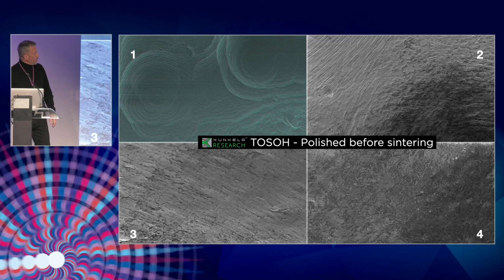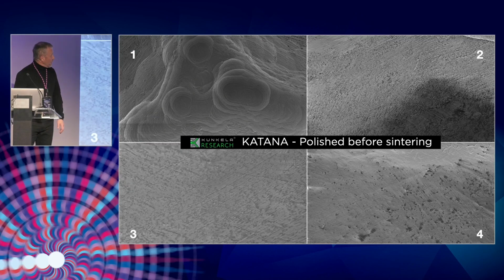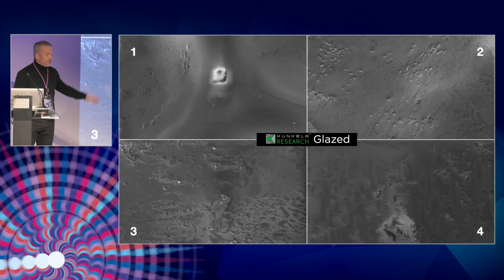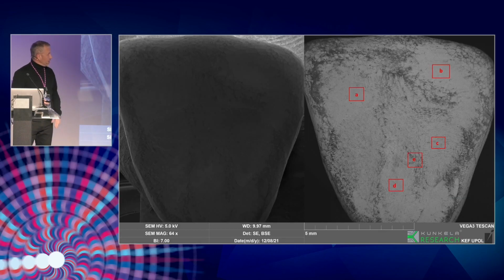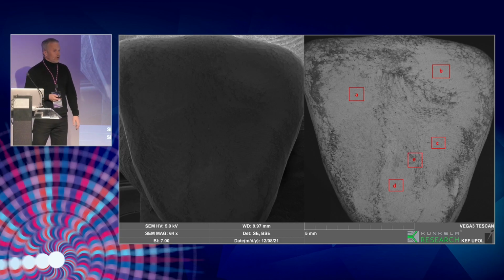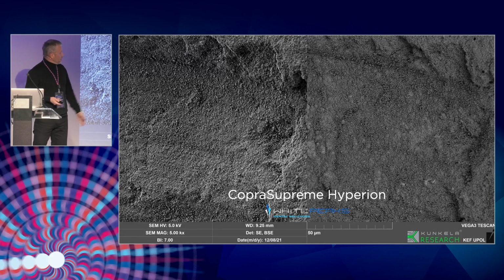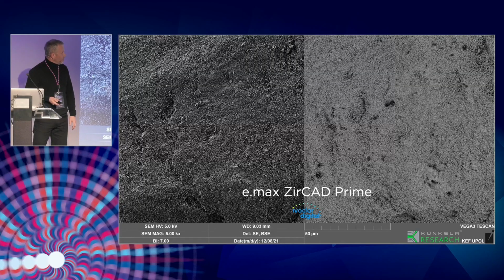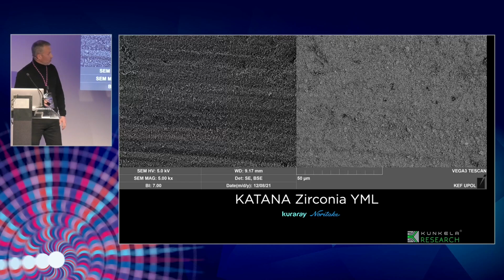This is how it looks when we polish before sintering, because it's good to polish the material in this soft stage, and again Katana looks really better. That's why we polish. Once it's glazed, it's invisible what is behind the surface. And you have already heard and seen an amazing presentation from my colleagues here on how stable the glaze is on the surface. It's really unpredictable. In the last three pictures, you can also see the difference in magnification with an SEM microscope of just the material between Tosoh zirconia, Emax Zircad Prime, and Katana zirconia YML.